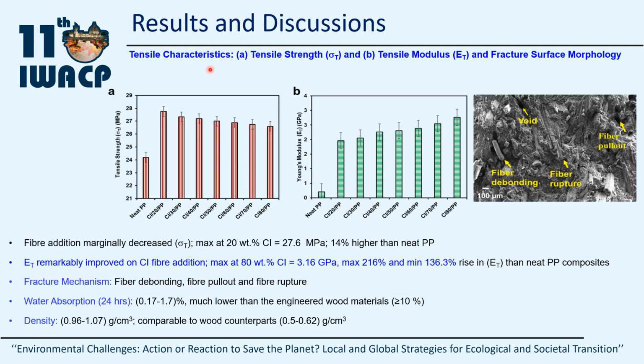In terms of tensile properties, tensile strength and tensile modulus were determined. The tensile strength of the CIPP composite exhibited a marginally decreasing trend with a maximum value of 27.6 megapascal. Young's modulus followed a similar trend to that of bending modulus, with a maximum value of 3.16 gigapascal, which is approximately 216% higher than neat polypropylene composite.